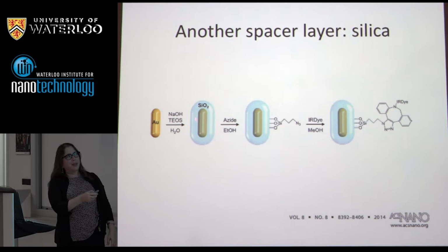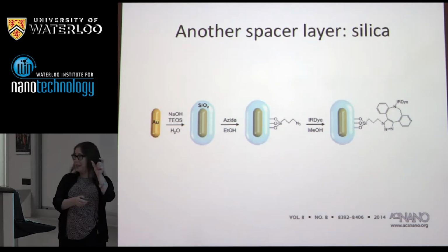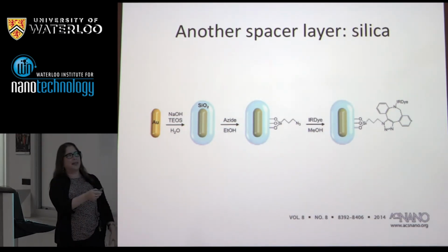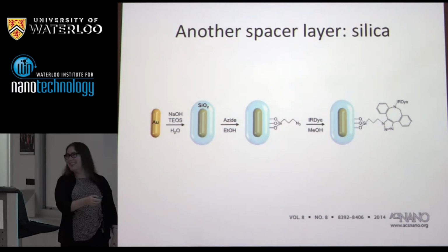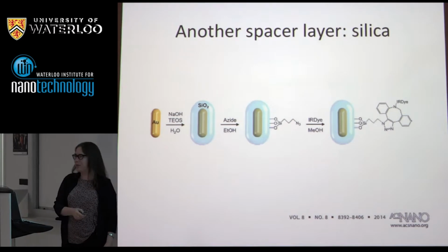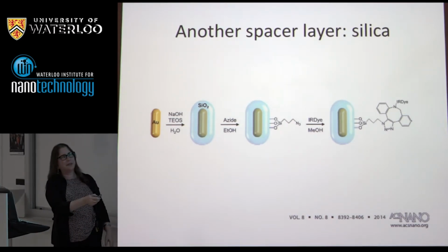We're going to take our rods and put on now a silica shell because we can make that significantly thicker, and I'll show you how we do that in a second. And then we're going to couple on a silane azide, which we had to make ourselves. Well, actually, we had an organic student make it for us because this is not commercially available. And then we can buy commercially this dye where you can do a click reaction and go ahead and put this whole thing on there.